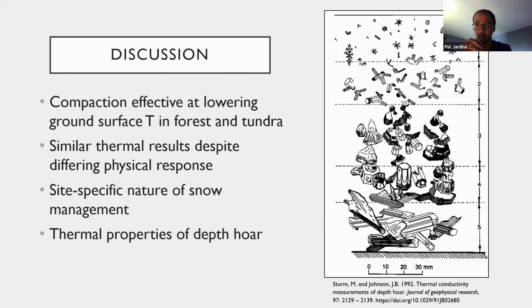So the difficulty with modeling thermal conductivity in tundra is not a new problem. At least as of 2019, detailed snow physics models, Crocus and SNOWPACK, struggled to simulate high Arctic snowpack thermal conductivity accurately. Both models simulate the snow as having high density and therefore high thermal conductivity, but field results have consistently shown the opposite: the tundra snowpack has high density, but also low thermal conductivity. And that's mostly because of that basal depth hoar layer at the bottom. The inaccurate simulation of this layer can throw model results off by up to 4 degrees.